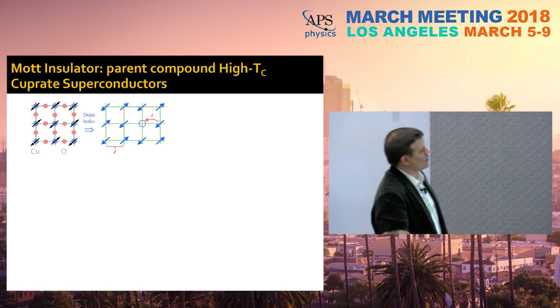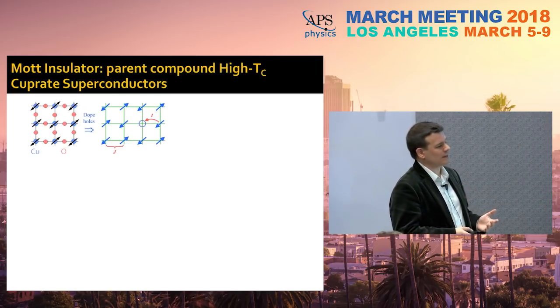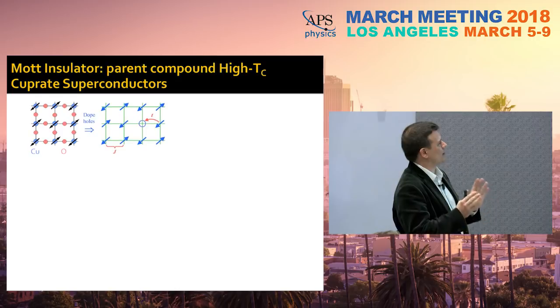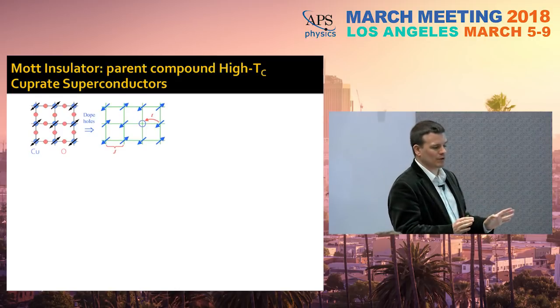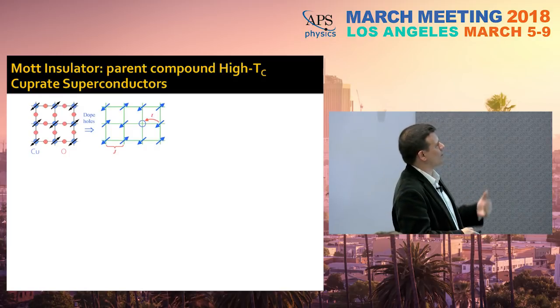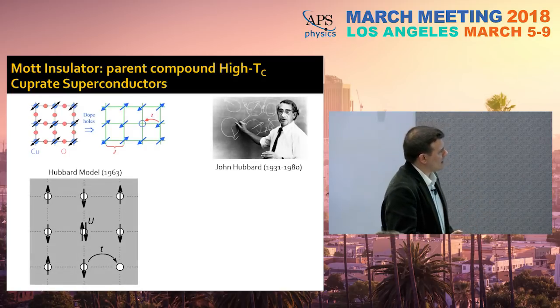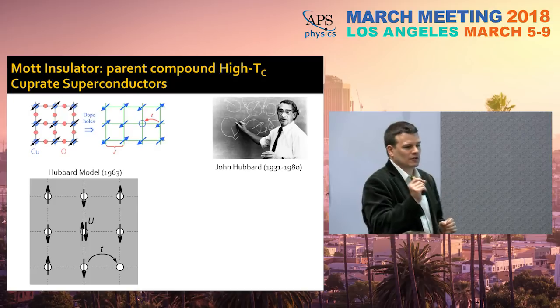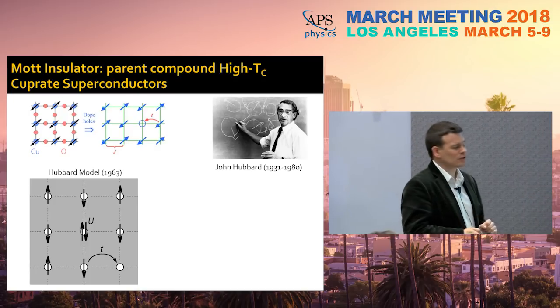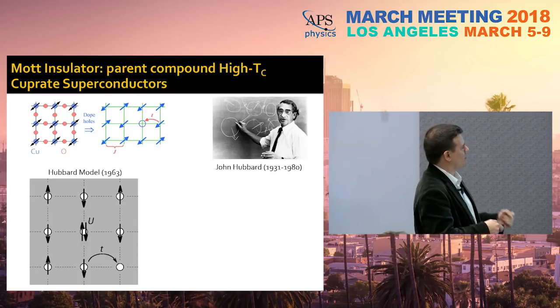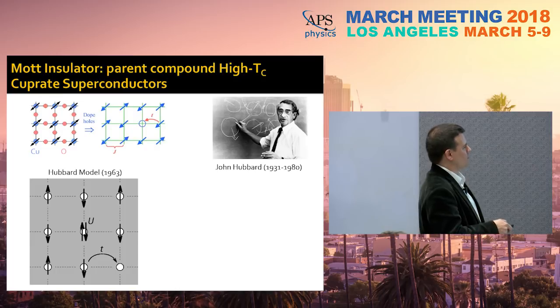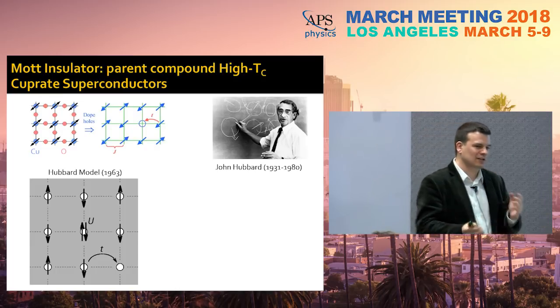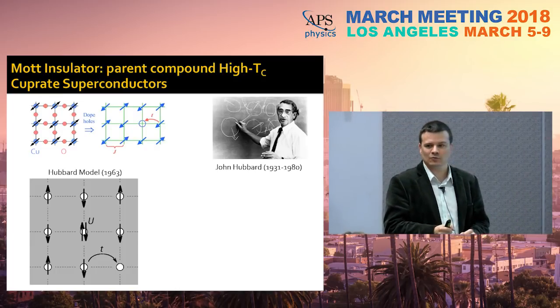Now, the Mott insulator state is the parent compound for stoichiometric high temperature cuprate superconductors. You have these copper oxide planes. If you grow them without any doping, you actually have a Mott insulator. And if you now remove electrons or add electrons to this Mott insulator, then you have this competition because you have an empty site. These electrons now can actually move. You still have to pay charging energy if you want to move into some of these sites. So now there's a competition between kinetic energy and Coulomb repulsion.